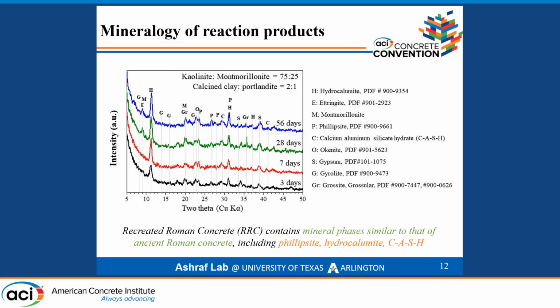Besides hydrocalumite, we have some calcium silicate hydrate and calcium aluminum silicate hydrate. And other than these phases, we have ettringite, gypsum, grossite, grossular, okenite, and phillipsite, which is a crystalline zeolite and which was also present in the ancient Roman concrete samples. And we have also some unreacted montmorillonites. However, the ettringite was formed at a very early stage. We did not notice any kind of crack or deformation of our sample over the curing period.